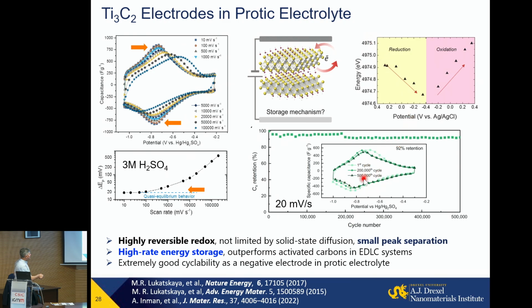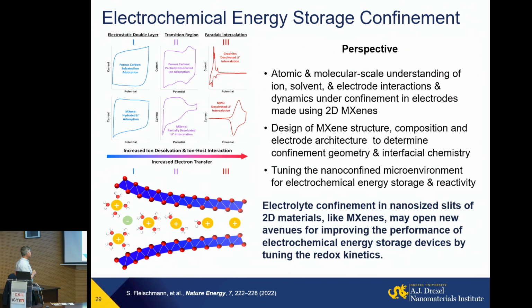Moreover, we were able to run a titanium carbide supercap in sulfuric acid electrolyte to 500,000 cycles. This is at least an order of magnitude longer compared to other pseudo-capacitive redox active aqueous materials, and it's only 8% loss, so we can certainly go to 1 million cycles, what carbon in organic electrolyte delivers. So it can be very, very stable.